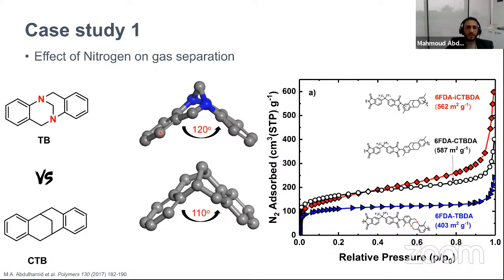So it's like V-shaped. When we grow a polymer out of this, imagine many V-shapes connected to each other, and another chain with many V-shapes connected to each other. Underneath you will see a space. So there is kind of empty space in between, and this is responsible for generating porosity. So we wanted to know what is the effect of this nitrogen. Is it doing anything that is useful for gas separation, or is it just there because we have this molecule? So we thought of designing the same exact structure but replacing the nitrogen atom with a carbon atom, and we came up with carbocyclic Troger's base. So carbocyclic Troger's base had a slightly lower torsion angle.